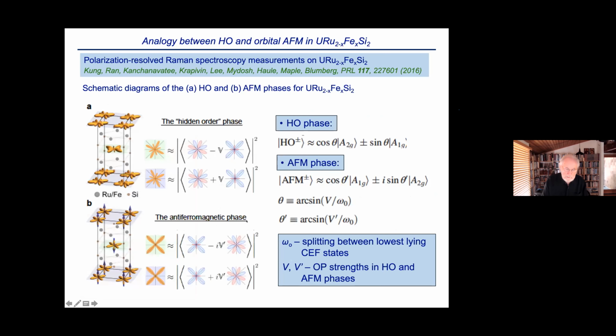And then finally, the interpretation is that in the hidden order phase, you get the superposition of these two wave functions, or these two singlets, that give rise to this chirality density wave. But in the antiferromagnetic phase, you can use the same set of wave functions and then generate an antiferromagnetic structure that also has a period doubled along the z-axis. And so here you see the magnetic moments, orbital moments, that are presumably associated with this ordered phase. So this is, I think, one of the more interesting candidates for hidden order.